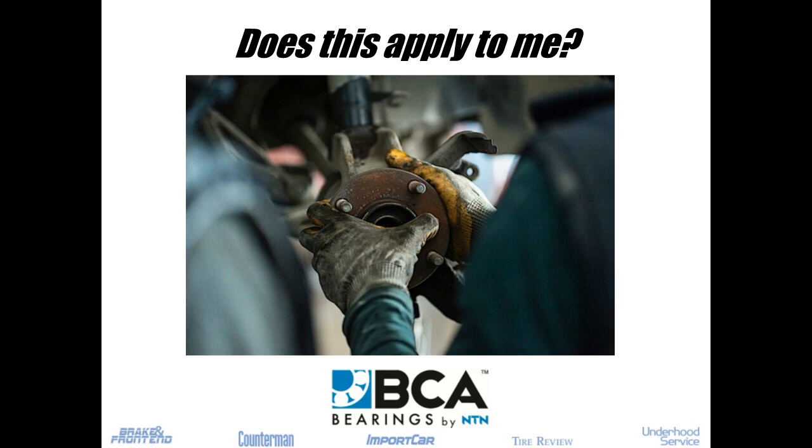I'll take that one. Definitely, because there's less of a cushion or less sidewall between the road and the rim itself. So it is causing issues with the wheel bearings taking a little bit more abuse. Because what typically happens when a vehicle hits a pothole is the rim can't flex like a sidewall. And this causes damage to the wheel bearing a lot more readily than if there was a nice thick sidewall on a vehicle with a 70 series tire and a 15-inch rim.